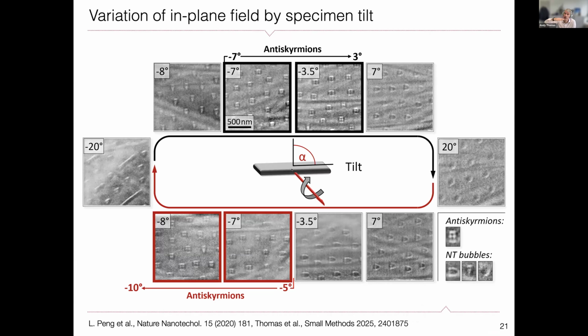So here we have bubbles, bubbles, bubbles, bubbles, and then at -7 degrees we recover the antiskyrmions. At -8 we still have the antiskyrmions, and then if we tilt more and more, the antiskyrmions go away. And of course, when you tilt back, they reappear pretty much at the same position. We are a little bit limited physically. You cannot tilt 90 degrees, and you would not have a TEM image, obviously, but our tilting range is limited to, I believe, ±20 degrees. And that's basically what you see here.